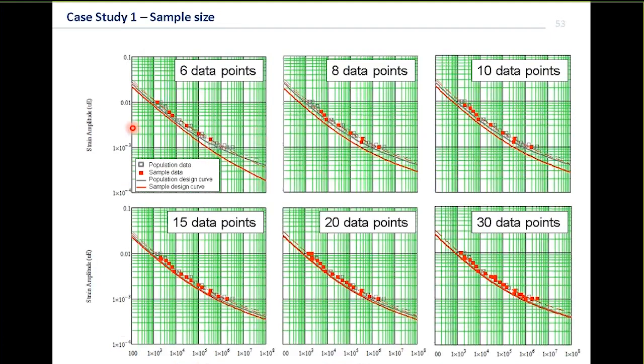Actually, the bigger problem with 6 data points is it's almost impossible to get 6 data points aligned evenly along the curve. They tend to come in clumps. So what you find is that in certain parts you'll get lots of points together, but then you end up with big gaps with nothing at all. So you've got no confidence in those. 8 points is pretty much the same story, and so's 10 points.